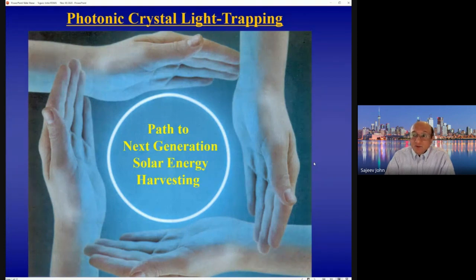And this important discovery has two remarkable consequences. First, it enables silicon solar cells to reach efficiencies as high as 31%, well above current world records. Perhaps more amazingly, this can be realized in thin, flexible films of silicon on the order of 10 to 15 microns. Now, many people use the words next generation solar.